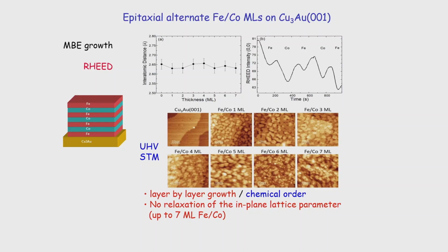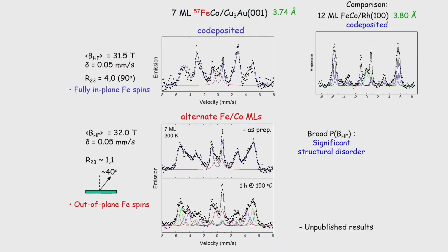Then we investigated the growth. You have very nice epitaxial growth, layer by layer, okay? And we went up to 7 monolayers. And this is the Mossbauer spectrum for a sample with 7 monolayers of iron cobalt, okay? This was a very rough measurement, but we saw that if you grow by co-deposition on rhodium, we have perpendicular spins. But if you do the same on Cu3Au by co-deposition, we see in-plane spins, but if you alternate, if you do some chemical order, we see a clear change in the spins, okay?